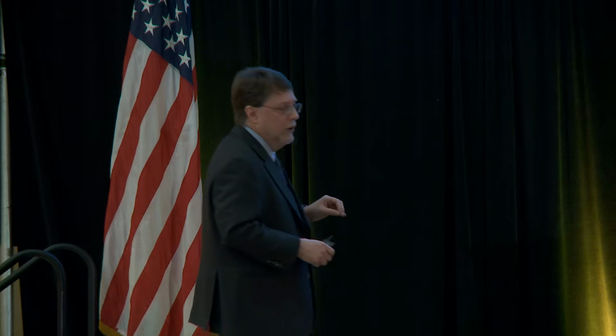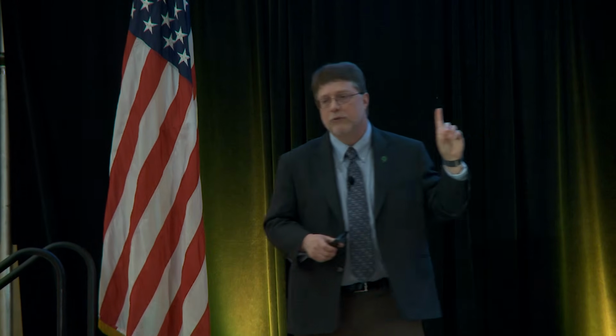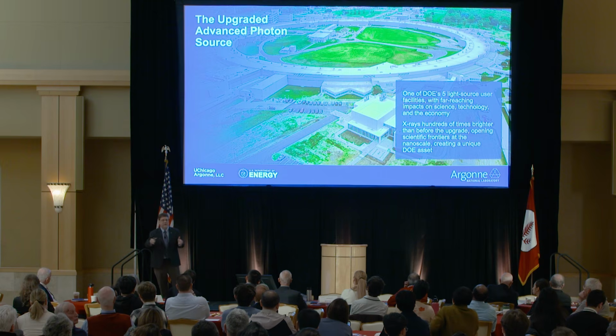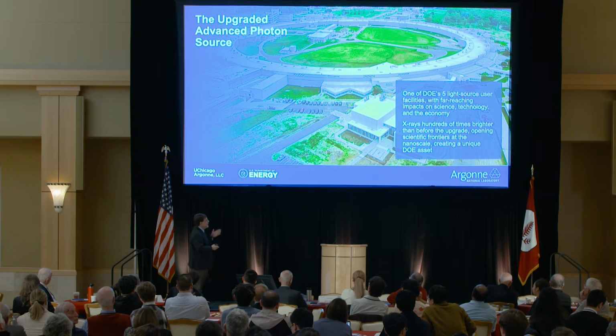And in about 2012 or so, Brian realized the design for the upgrade project for the APS was the wrong design. And through a Herculean effort of not just Brian, but many people at the APS, they redesigned the magnetic lattice for the facility and dramatically shifted the future of the APS from what had originally been basically a beamline upgrade to something that replaced the storage ring with something called the multi-bend achromat lattice, that increased the X-ray brightness and the coherent flux by somewhere, depending on the energy you're looking at, around a factor of 500. And that is transformational in what you can do with that. So Brian had his period as the APS director. He stepped aside and I took on after him.